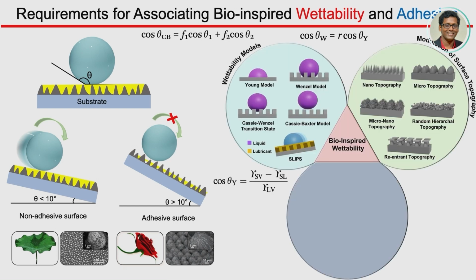And believe me or not, this kind of ability of tuning these adhesive and non-adhesive properties is mostly done in the literature by modulating the topography, and that is not an easy job. When you are dealing with large scale production, it is really difficult. Though we have really advanced nanotechnology where you can precisely control nano and micro domains, when it comes to large scale production, it's a problem, right? So we thought, not topography, let's take another avenue, that is the chemistry. In this particular field, mostly people focus on the topography, not really on the chemistry. The chemistry part is kept very blunt. What I mean is that mostly people look for a long hydrocarbon tail or its fluorinated analogs, right? Just to satisfy the low surface energy.